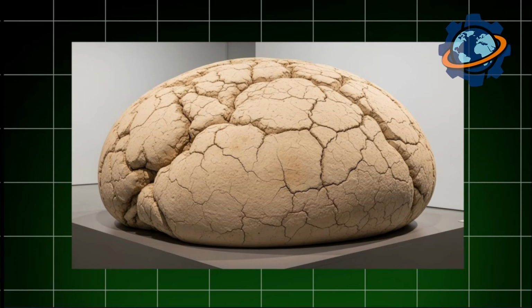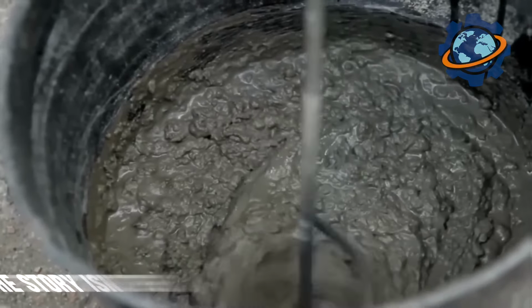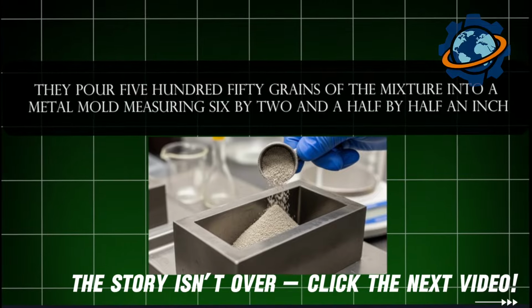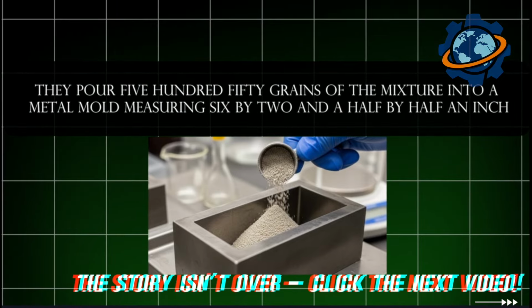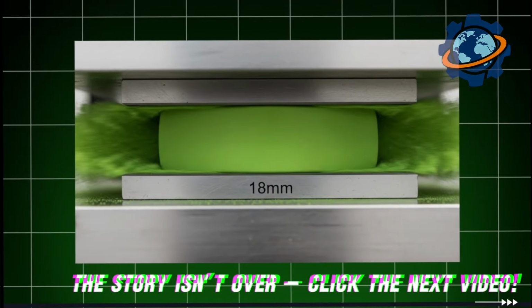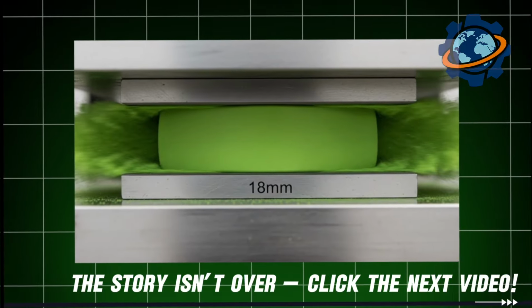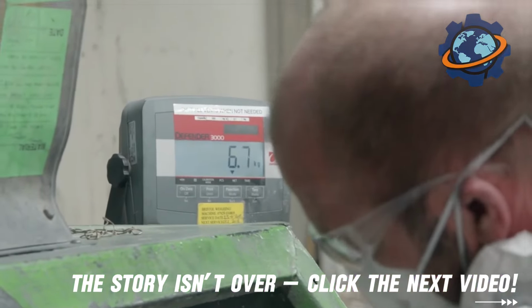The mass goes into a rotary press, a machine with 20 tons of force. They pour 550 grains of the mixture into a metal mold measuring 6 by 2.5 by half an inch. The top plate descends with 285,000 pounds per square foot of pressure, like parking a tank on your palm. In 10 seconds, the dough compresses into a monolithic green blank, 3/4 of an inch thick. The pressure squeezes out all the air, creating a density of 175 pounds per cubic foot.